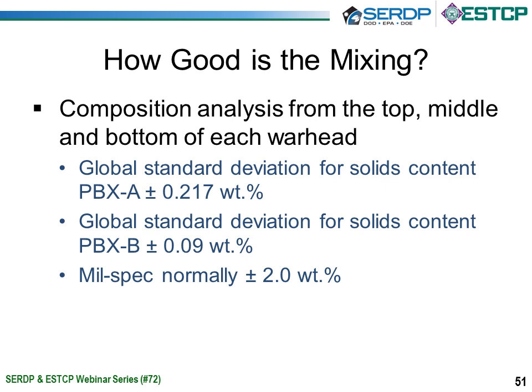The global standard deviation: we mixed this material in that three warhead configuration, three warheads at a time, and then we sampled those warheads rather than curing them, at the top and the middle and the bottom of each warhead. We made triplicate measurements of the composition of the explosive particles in there, and we ended up with a global standard deviation of all of those measurements of the number that you see there, 0.217 weight percent.